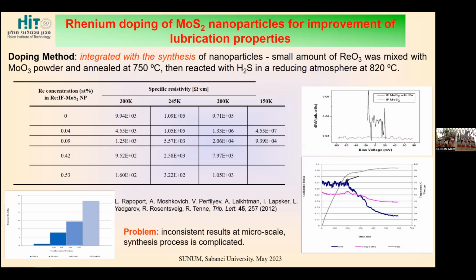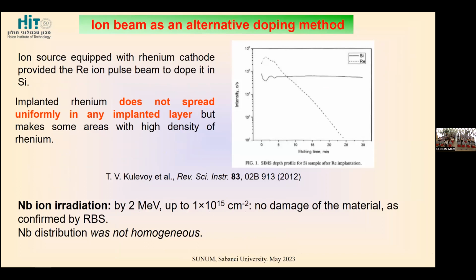So first of all, the doping methods. We did not arrive at gallium implantation by focused ion beams immediately. We tried different chemical methods, and these chemical methods, for example with rhenium, were quite successful in decreasing the specific resistivity of our nanotubes. This was very beneficial for their lubrication properties because of Coulomb repulsion. But the process was chemically quite difficult. Then different ion sources were used for both rhenium and other atoms implantation, but the distribution of these atoms was not very homogeneous and the results were not continuous.